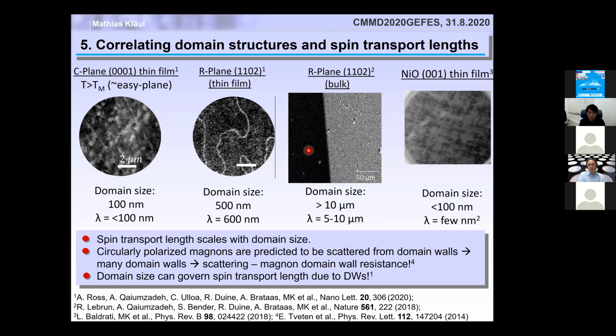The other thing that we also saw is that some of the surfaces reconstruct differently from others. So this can also play a role in the formation of domains for thin films. For bulk, I think it's simply the quality of the crystal. And there's some nice work from Helen Gomonay, who has shown together with Eric Folven that if you have nano-patterned structures, you can get strain relaxation at the edges, leading to some kind of shape anisotropy. But I think the answer primarily is the quality of the system if you have unpatterned, continuous systems.